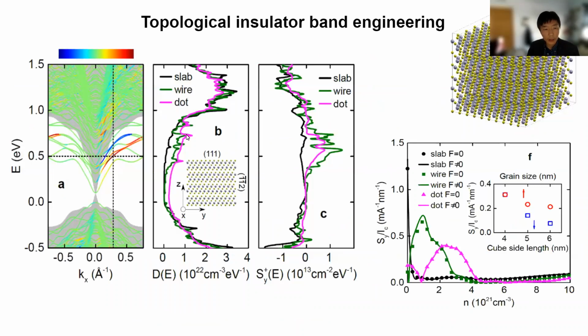Here is a study of the density of states and the local density of states, and in this case the integrated density of states and the spin polarization on the surface. Now we want to analyze the case of a quantum dot. Because in this quantum dot you don't have periodicity in any dimension, we can't plot the band structure. But by looking at the density of states, especially the Van Hove singularity, we are able to identify the energy levels of those quantum dots.